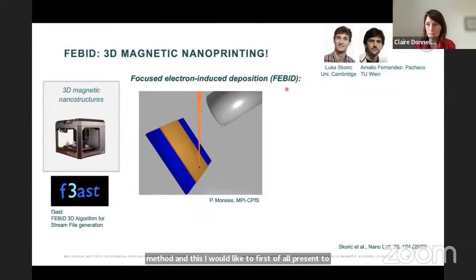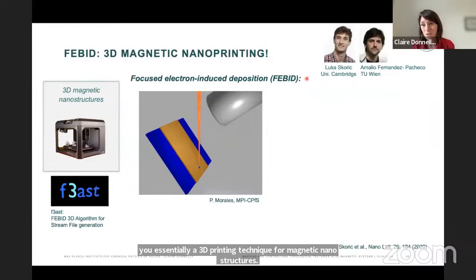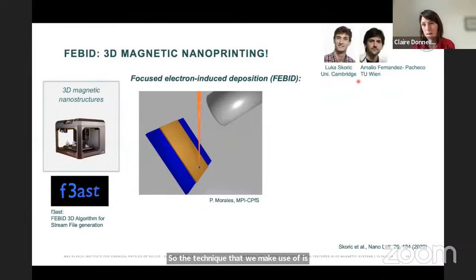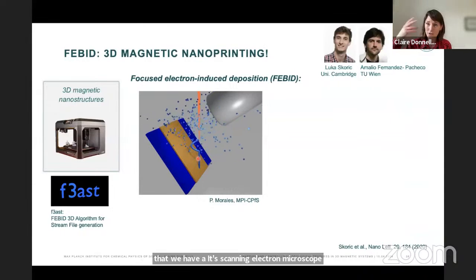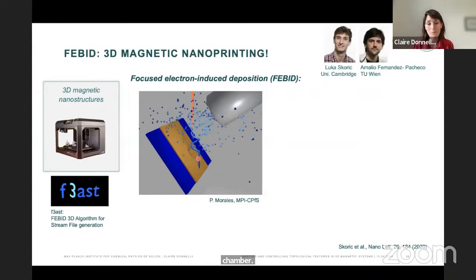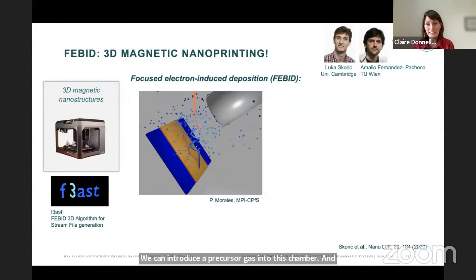The technique that we make use of is focused electron beam induced deposition. This 3D printing with FEBID was developed by Amalio Fernandez-Pacheco, who's now at TU Wien. The idea is that we have a scanning electron microscope chamber, we introduce a precursor gas into this chamber, and with the focused electron beam, we can locally deposit our material.